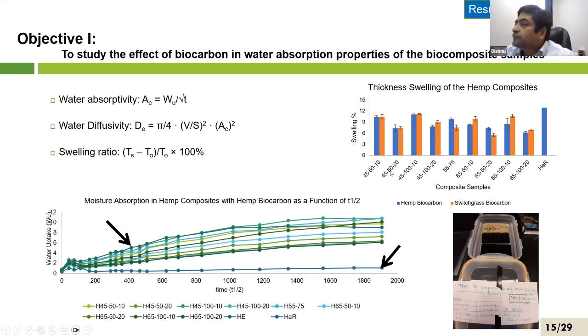That's fascinating. And then I think 50, 100 could be the two particle sizes that we are using. Oh. And then H45 might represent the 450 °C biochar sample. So that means we produced the biochar at 450 °C versus 650 °C. So we have one at 450, one at 650 °C. Okay. Thank you.